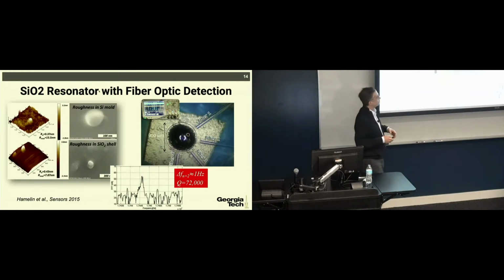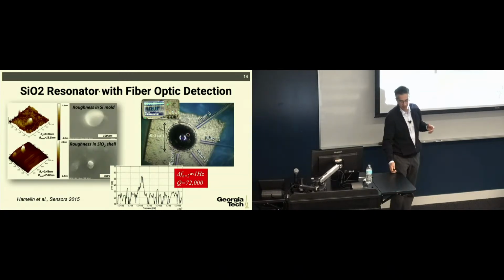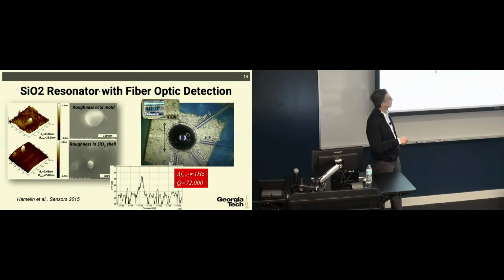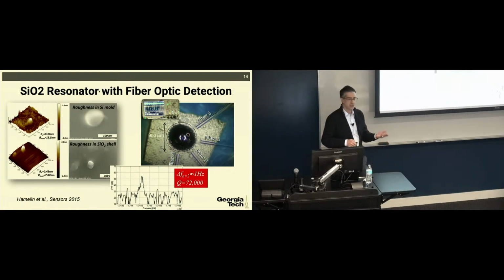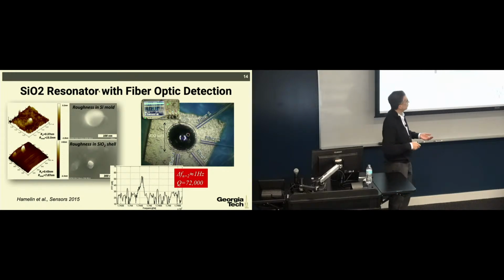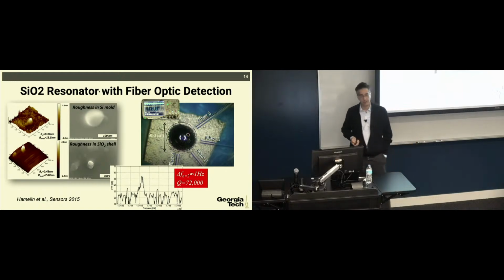And then it was very hard to have integrated transducers. So what we did to excite resonance and sense it was that we put optical fibers around the perimeter of this shell resonator, and then started shaking it on a piezo stage to excite the resonances. And what we realized was that we could actually see the resonances of the gyroscopic modes. The Q was not as high as we anticipated it to be.